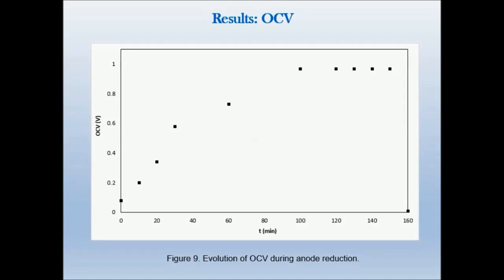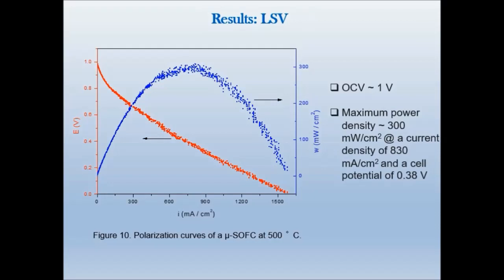For this sample, 2 hours after the anode reduction was started at 500 Celsius, linear sweep voltammetry measurements were performed. On the polarization curves shown in this figure, the open circuit voltage is close to 1 volt. The maximum power density is about 300 milliwatts per square centimeter at a current density of 830 milliamps per square centimeter and a cell voltage of 0.38 volts.